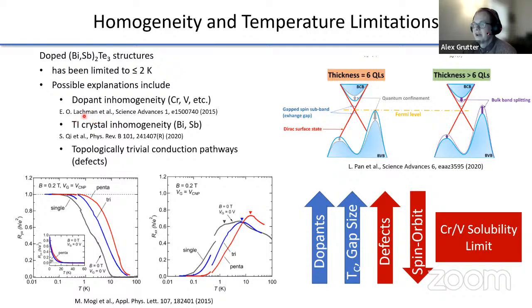And some really interesting work by Lachman et al. in 2015, they did scanning SQUID measurements that showed that you have, in fact, all these sort of superparamagnetic regions rather than a single uniform magnetic state. Now, on the other hand, some recent theory calculations by Qi et al. demonstrated that you also have to worry about the inhomogeneity in the crystal itself. So bismuth and antimony in bismuth antimony telluride have a tendency to cluster themselves so that you don't actually have a homogeneous mixing, but you have some bismuth and some antimony, and this can lead to variations in Fermi level position and gap size as well that can cause problems with and suppress your quantization temperature.